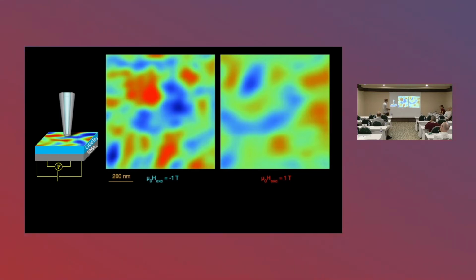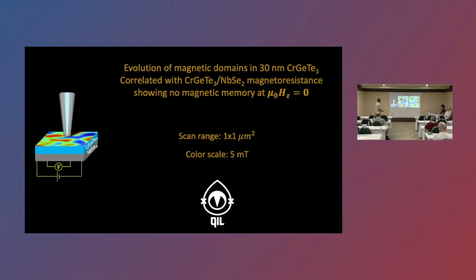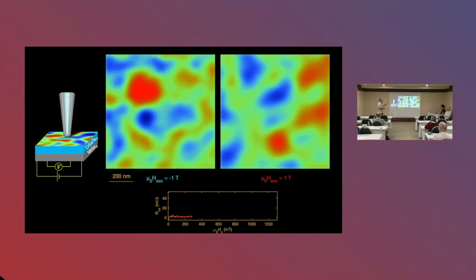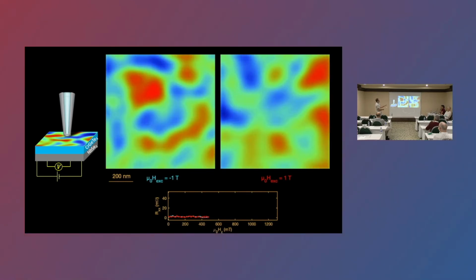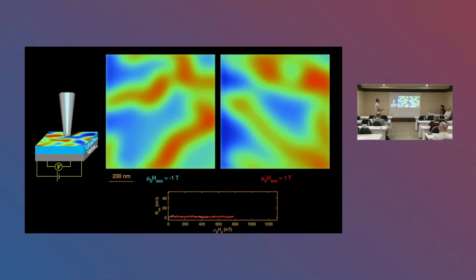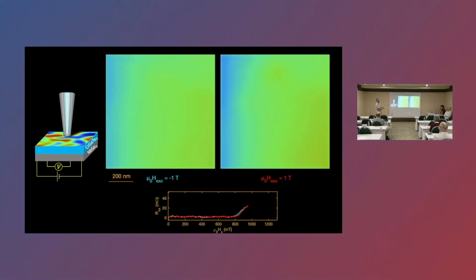So you need another probe that is more global to tell you what the state is. Here I will again show you the transport data for these two samples going up. If this sample has more domains pointing up because it was at +1 Tesla, it should magnetize more easily in that direction, because there will be more domains pointing that way with respect to this one. We can look at both the images and the transport data. Now I will run the movie again. As you can see, both in the images and in the transport data, these two things coincide with each other, which means essentially that the sample has no memory. At zero field, magnetically, it doesn't know if it was at -1 Tesla or at +1 Tesla before, way above the saturation field in both cases. It starts from zero. It doesn't know. So it's not magnetized.